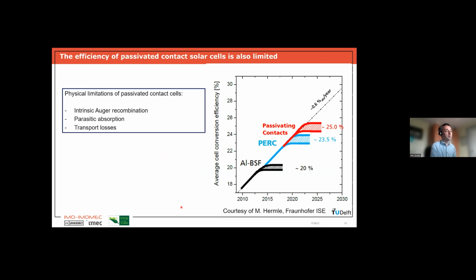So if we go back to the roadmap, we see that with passivating contacts, we can make a next step. We can probably reach in industry for mass production efficiencies of around 25%. Of course, again, every cell concept will have its particular limitations, but it becomes tougher and tougher to overcome those limitations. So here, one of the limitations is that we might still have quite a lot of optical losses, so-called parasitic absorption losses. And to overcome that, the next step could be to go to back junction solar cells.